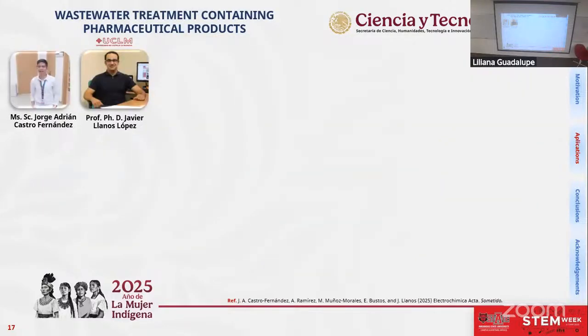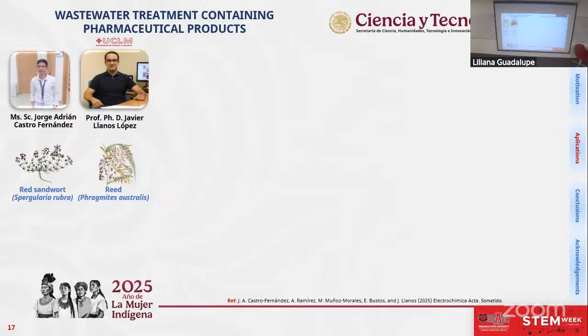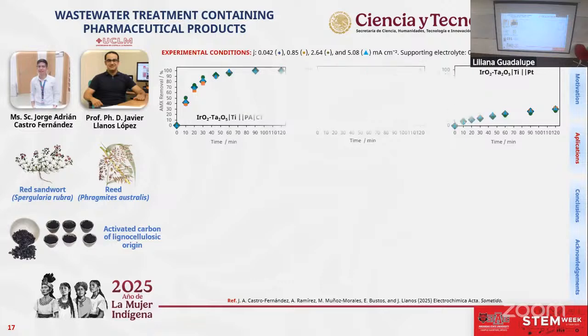So actually, we are working with the University of Castilla-La Mancha in Spain, with Professor Javier, and Adrian developed different surfaces involving waste. This is very nice because these are plants that you can find in Castilla-La Mancha, and they are only waste in the city. So they prepare activated carbons with this waste and promote the modification of electrodes, in this case, the cathode. So with our iridium-based anodes, we use both electrodes to increase the efficiency of the removal of the pollutants.